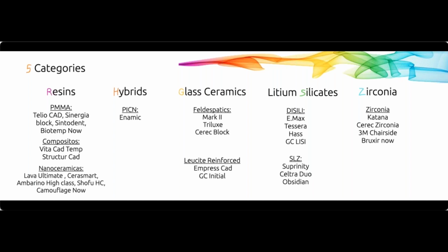Then you have glass ceramics, which are just a piece of glass, very amorphous, very porous, beautiful, but brittle. And then you have lithium silicates, which are not as beautiful as glass ceramics, but very close, but a little bit tougher. The tenacity of it is higher because of those crystals that grow. You need to put them in the oven. They're really hard to hand polish, not impossible, but really hard. So you actually have to glaze them and stain them. Since you're going to put them in the oven, might as well do it anyway.